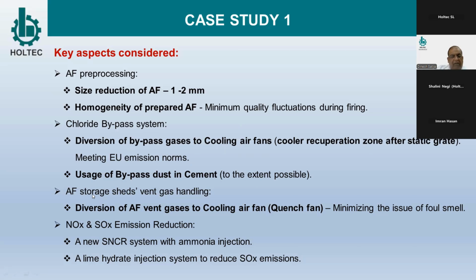Similarly, the alternate fuel storage shed vent gas, which many times is vented into the air, here all those gases were taken and put into the cooler area, through the quench air fan. So that was used for quenching, and it also minimizes the foul smell issues which are very common in such AFR feeding areas. All the foul air was fed into the cooler. Plus for NOx and SOx, SNCR and a hydrated lime injection system were already provided there.